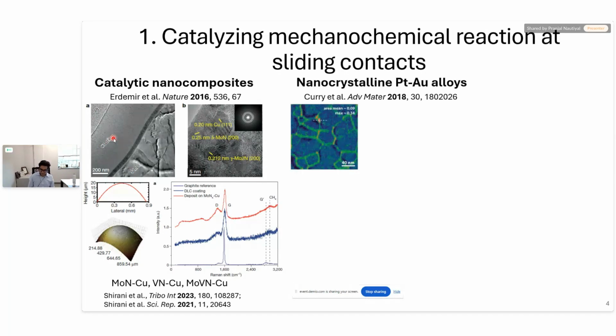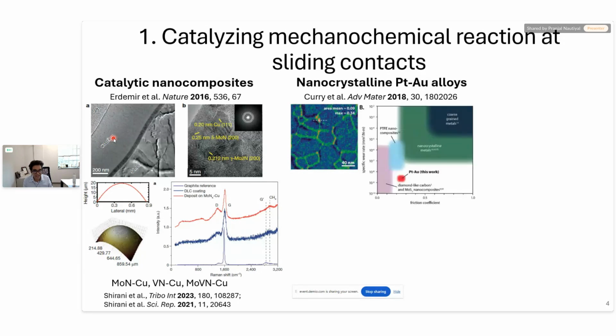Apart from this, there has been some work on nanocrystalline platinum-gold alloys from Sandia National Lab. So these are nanocrystalline alloys. They consist of platinum and gold, where the gold atoms segregate at grain boundaries and make these nanocrystalline alloys highly stable, preventing grain growth. So the researchers at Sandia, John Curry and co-workers, did wear testing of these nanocrystalline alloys.